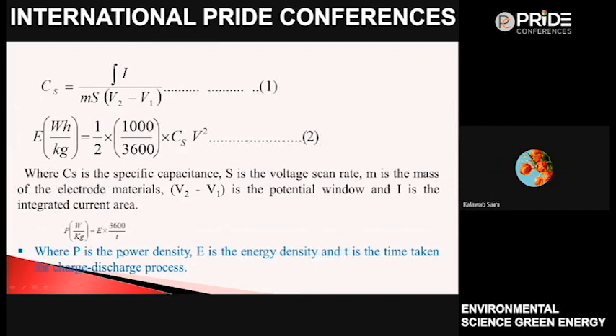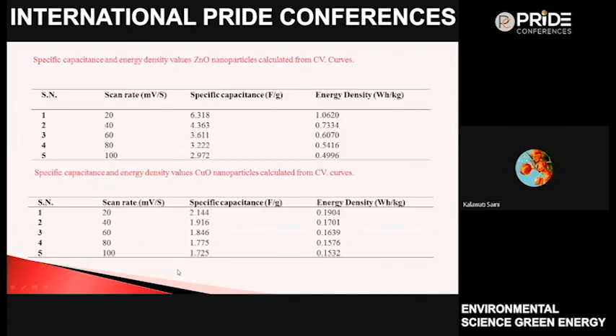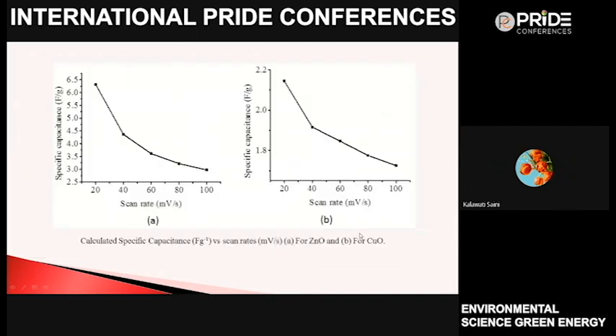And here P is the power density, E is the energy density, which is calculated by this formula, and T is the time taken in the charge discharge process. These are the results regarding the first table regarding zinc oxide and this is regarding copper oxide. The energy density is higher for zinc oxide than for the green synthesized copper oxide.